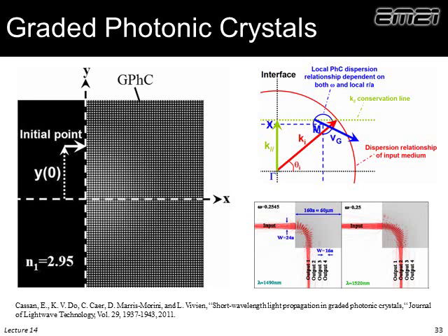We have graded photonic crystals, and these really come in two different flavors. The one really isn't even a photonic crystal, but imagine we have a distribution of holes, a lattice of holes, and the spacing is so sub-wavelength that it's really not a photonic crystal. There's no wave scattering. We chirp the size of the holes. We can essentially grade refractive index, and in fact, we can bend beams through lattices like that.